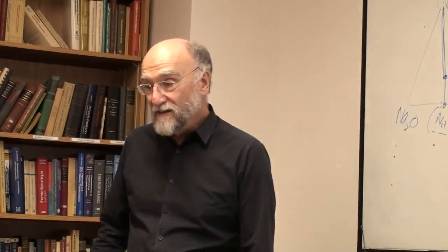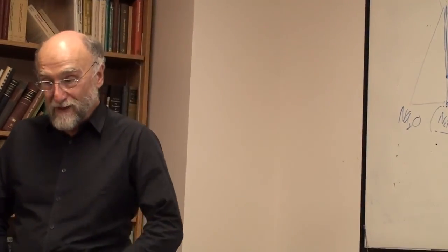So that certainly is not everything you could learn about slags, but that gives you an idea. We use the quasi-chemical one sublattice model here, except when we put in sulfide ion, and then that goes on the sublattice along with the oxygen, except sulfur, of course, does not form a network. Sulfur is always S2-, even in pure silica. The sulfur doesn't form bridges between silicons. It remains ionic, which of course makes life more complicated when you're over at that corner. But Yunbei Kang, who was with us here for some years, has done a really good modeling job on the sulfide and oxide and silicate slags, all the way up to the pure sulfide side.